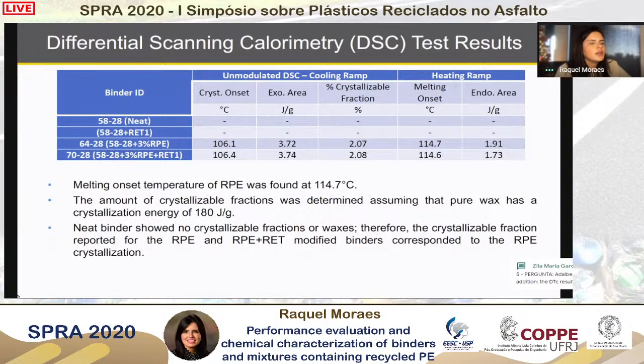Well, we know that when we have materials that have a high wax content, we have very, very different rheological performance. And by adding the recycled plastic, we can be increasing the overall resin content on the binder, therefore increasing the content of wax and changing completely the rheology of the material.